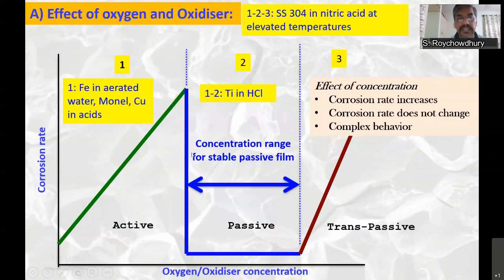The second possibility is that the corrosion rate increases, and when the oxygen concentration exceeds a certain minimum value, the corrosion rate drastically falls again. It maintains a very low corrosion rate for a wide range of oxygen concentrations. This is again because of the passivity that I explained in the previous slide. If the concentration becomes too high, it goes into the transpassive range, where the passive film degrades and dissolves. Titanium in HCl shows only regions 1 and 2, so even at very high acid concentrations transpassivity is not seen. Whereas in SS304 and nitric acid, you can see all 3 regions depending on the concentration of the oxidizing environment. So this was the effect of oxygen.